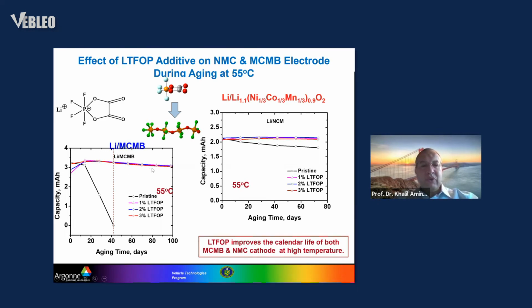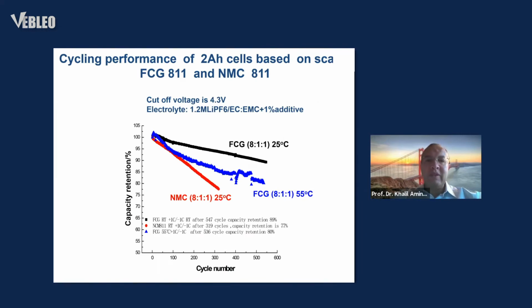And then when we test it versus carbon at high temperature, you can see with the conventional SEI, the capacity goes down, while with the new SEI that we form, we have very stable material for almost 100 days of aging, so very robust. So we use this additive in collaboration with our industrial partner that scaled up this material, and we use an aggressive composition, which is FCG 811 versus NMC 811. So the industry, by the way, is trying to enable this material in the next generation electric vehicle, because this material provides very high capacity versus NMC 622.